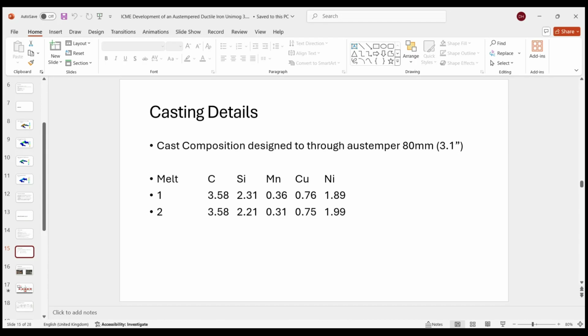But then we add manganese. We normally look at around 0.3, which depends on the foundry itself. Some of the smaller foundries use a lot of pig iron, so they run lower manganese contents, whereas higher volume foundries often use more scrap steel, so they run a higher manganese content, maybe 0.4 to 0.45. Then we add copper, and then nickel. In a worst case, if we have sections above 90 millimeters, we have to add molybdenum as well.